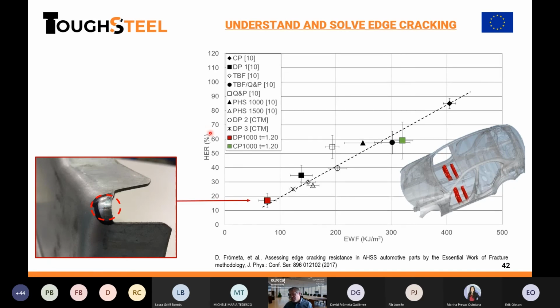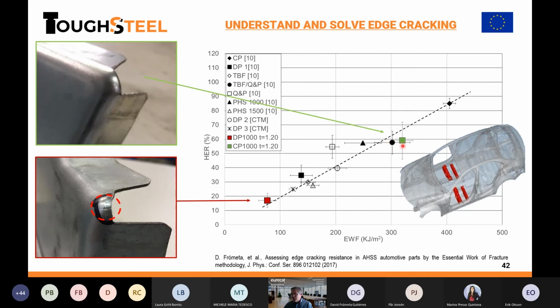This is the same as the last slide. This is an example of underseat beams in a vehicle. The first material was a dual phase with its crack clearly seen here. If you look at the curve I showed you before, hole expansion ratio versus essential work of fracture, this is the point, low toughness. But if we use a complex phase material with a higher toughness, no cracks. And this is consistent with different materials we tried: high strength steels, aluminum alloys, stainless steels, soft materials. So in any material we tried in the last 5 years, this trend is followed. The higher the toughness, the higher the edge cracking resistance.